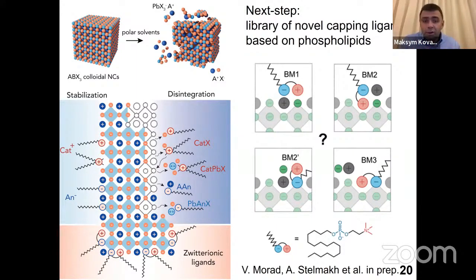And so then we thought, several years ago, how to run this ligand functionalization in a softer manner, and yet bind our ligands even stronger. So we came to the idea to use zwitterionic ligands, where you have a positively and a negatively charged group in one molecule. Now this group will attach to the surface by displacing a pair of cation and anion at the surface. And that worked. One example is lecithin. It's a natural phospholipid. You find it in chocolate and in many other products, very cheap. It works wonderfully.